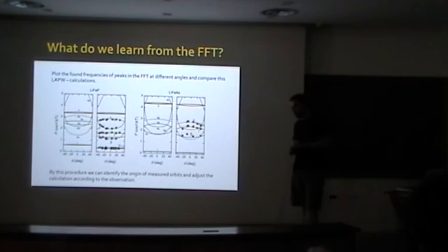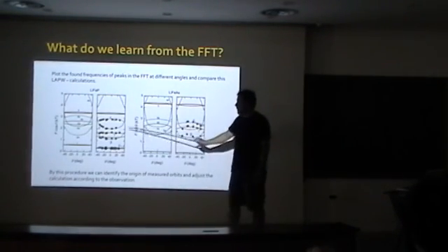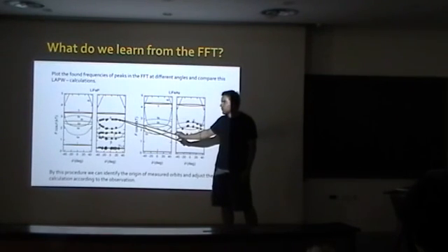In your experiments, when you see a frequency, you have a number. When you don't see it, can you estimate the limitation, which is the scattering for the given band? Because we know that in these systems, the scatterings are not the same for all of them. Yes. So if you have a band with large scattering, at which level would you suppress the oscillations? If we compare the data that we have on those bands and argue why we do not see this band, if the scattering rate on this one were about 10 to 20% higher than on those bands, we would already not see it anymore.